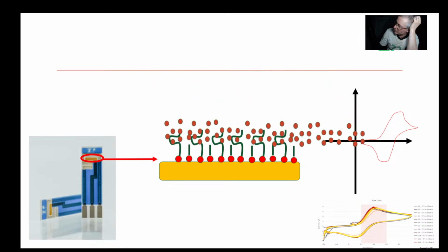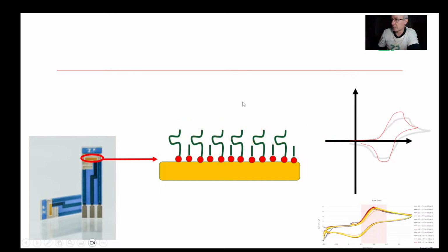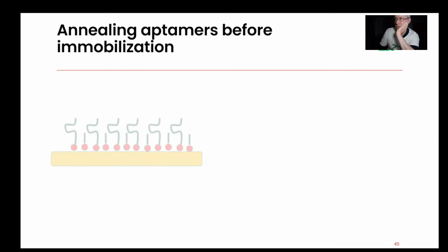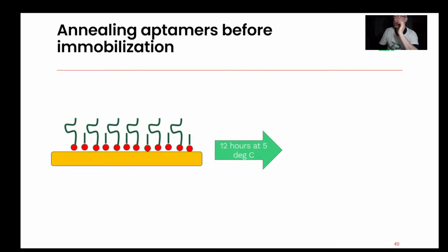Now, what I'm describing is something that we do hundreds of hours of at ZP per month. So what I'm describing is not in the abstract. As you add those thiols on, the cyclic voltammetry should get distorted because you're essentially blocking the surface. You mentioned annealing.